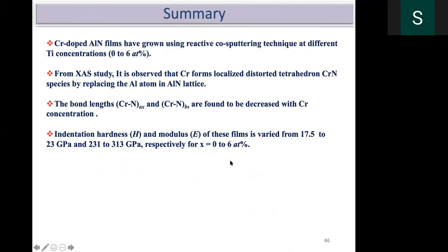Well, in this case also, I just wanted to conclude that we have grown aluminum nitride systems with different chromium percentages, and the X-ray absorption spectroscopy shows that this is also a distorted tetrahedron structure. There is a small difference in the refractive index, which I did not show here, compared to titanium and chromium. Chromium is better than the titanium-doped system. That's what we have seen. And of course, hardness, this is only on the top surface, but varies between 17.5 to 23 GPa by adding chromium to the system. One last slide.